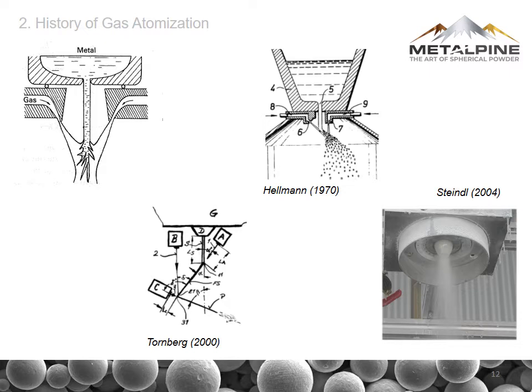To decrease particle size and to achieve narrower particle size distributions, Hellman, for example, did the attempt to have something like an asymmetric atomization system. The first gas flow 6 here, turning the melt jet, the open jet into a film, which is atomized by the second gas stream, number 7 here, vertically downwards. Tornberg in the year 2000 even used 3 gas streams A, B and C to have a better pre-filming effect and finer particles at a narrow particle size distribution.